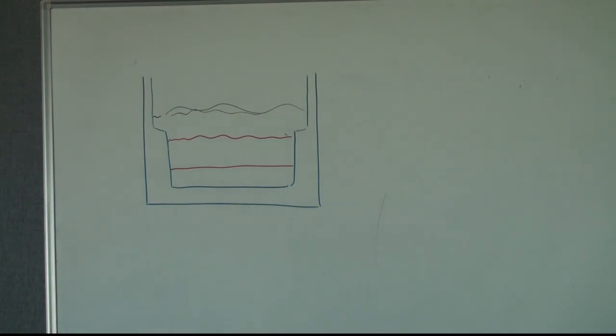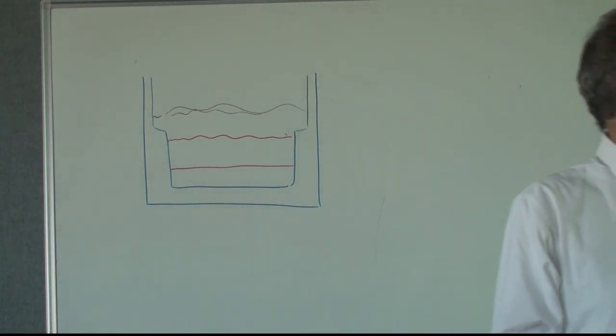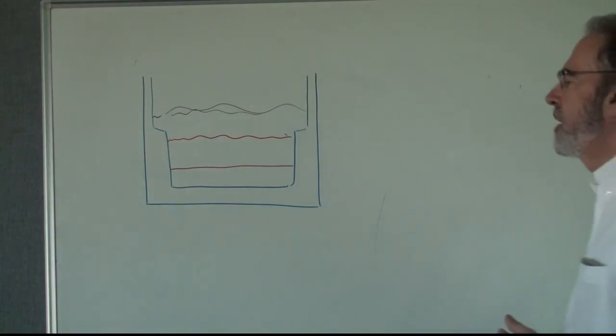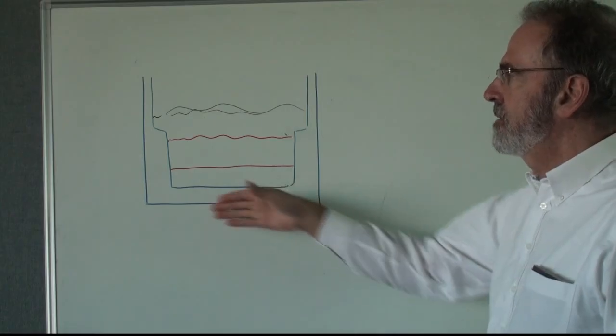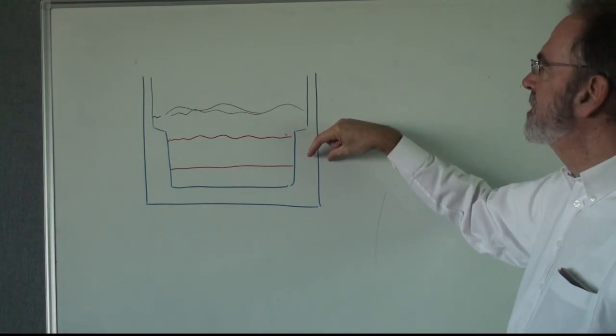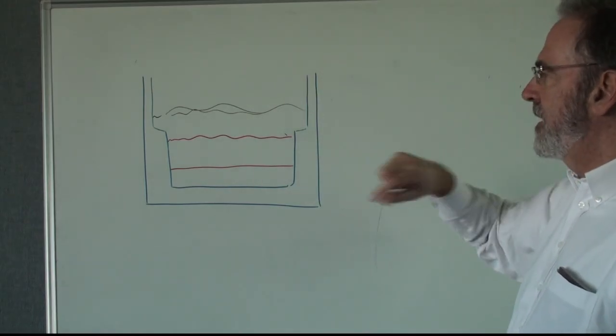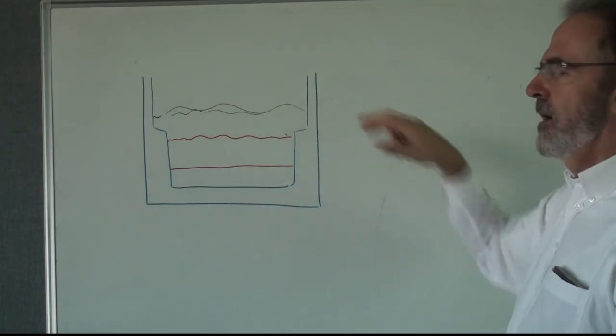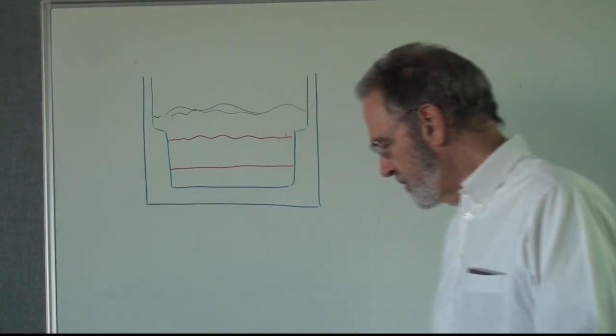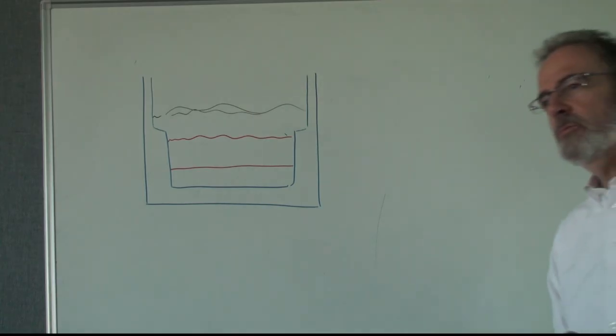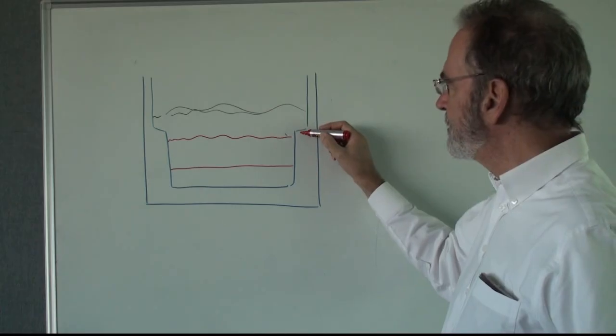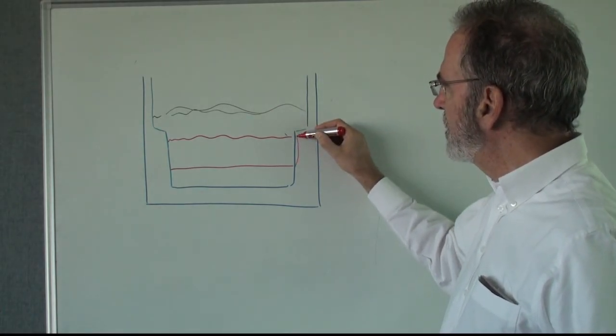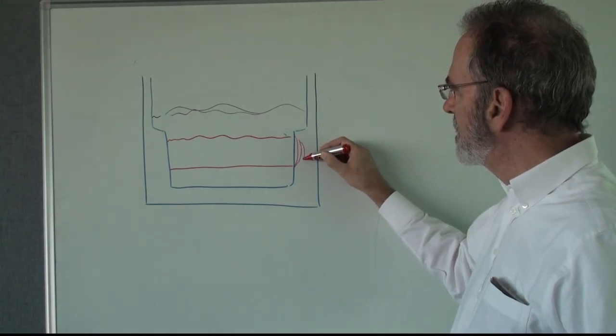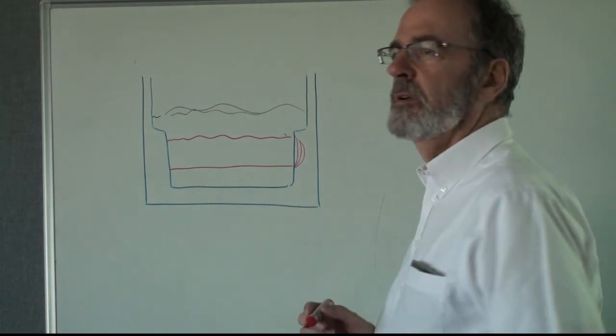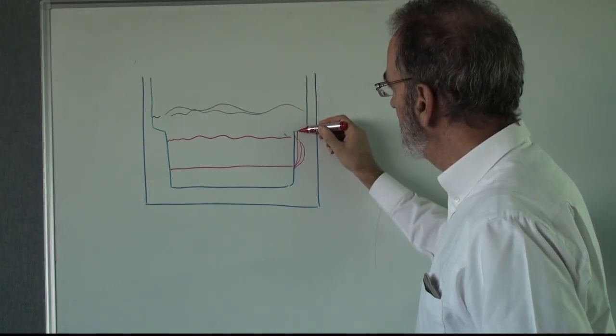Okay, this is showing you more or less the shape of the refractory over one furnace, exaggerating a bit the large parts and the smaller parts, and it's showing the different areas. This is metal, slag, and solid charge. And of course, the part which is submitted to the strongest wear is the slag part. So the wear of the furnace is going like this. And of course, when this descends, then it was this actually.